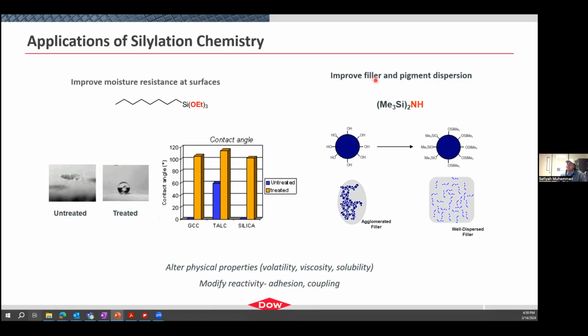We often use it to improve filler or pigment dispersion. So there's many different formulations that are very complex, like the paint that's on a wall, right? You put fillers in order to get certain performances, or you put pigments in. And if those pigments have a polar surface, they'll often clump together, and so they won't disperse very easily. So we can actually silylate those surfaces in order to have better dispersion for better mixing.